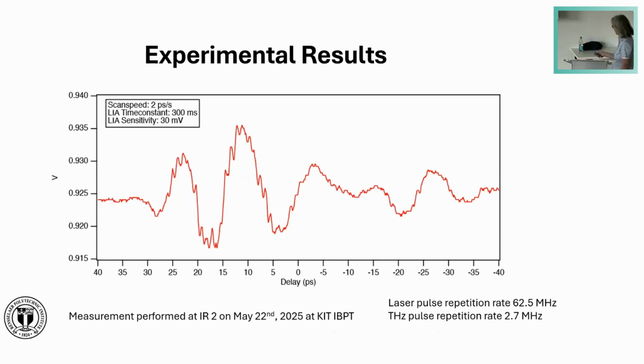We found a signal. This is a terahertz wave transient emitted by the synchrotron. We see here basically 30 picoseconds. It's a rather long event, with a trailing part of almost 60 picoseconds. And then we have a main cycle of around 20 to 25 picoseconds. We just did this last Thursday. In this measurement, the laser pulse repetition rate is 62.5 megahertz. The terahertz pulse repetition rate is 2.7 megahertz. So only 1 out of 23 laser pulses actually detects the signal.